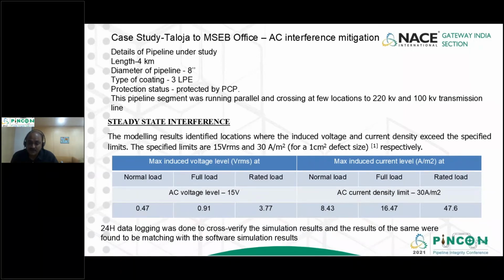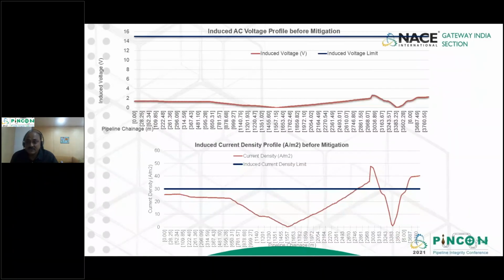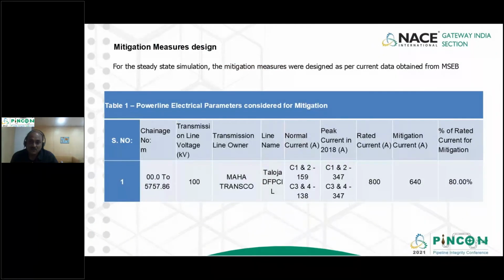So 24-hour data logging was done to cross verify the simulation results, and the results were found to be matching the software simulation results. And then, if you see this graph, the induced voltage and the induced voltage limit, and the current also. The current density in the section between 2968 and 3243 was very high, around 45 against the required 30. So once we got this confirmation, the next thing was we needed to do the mitigation.